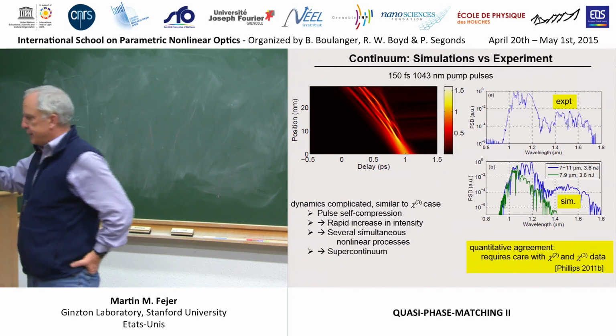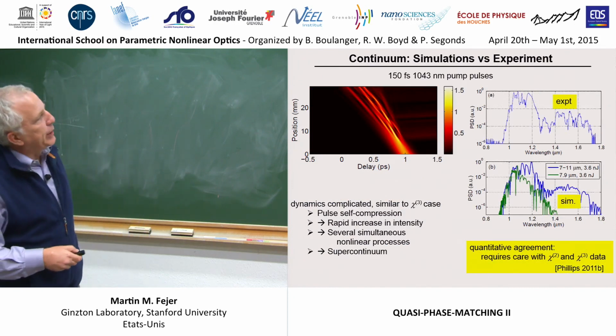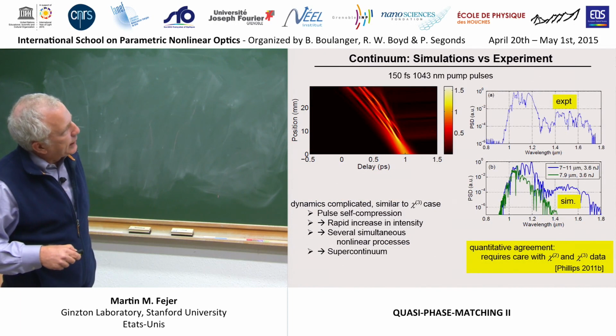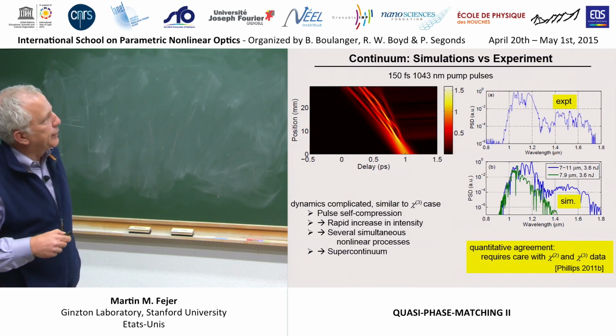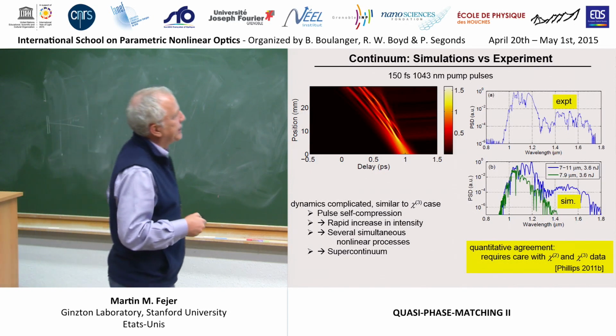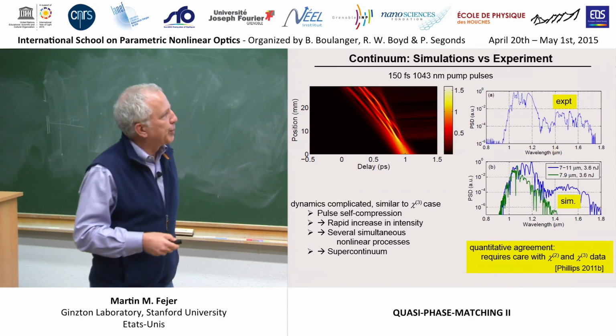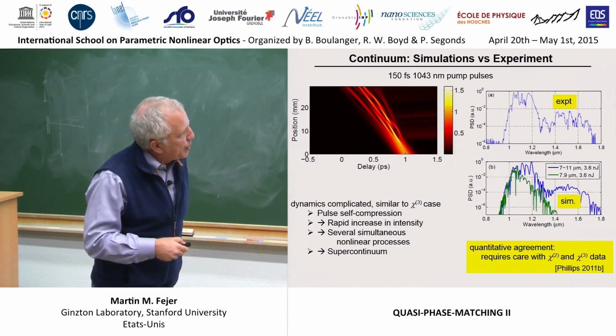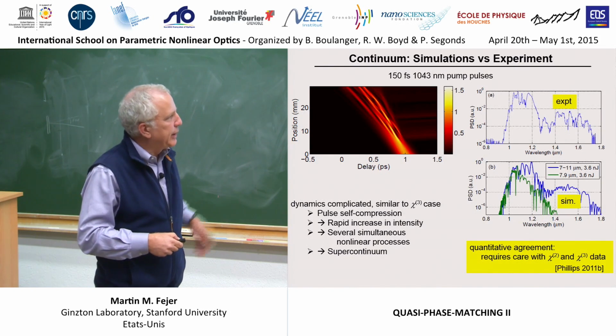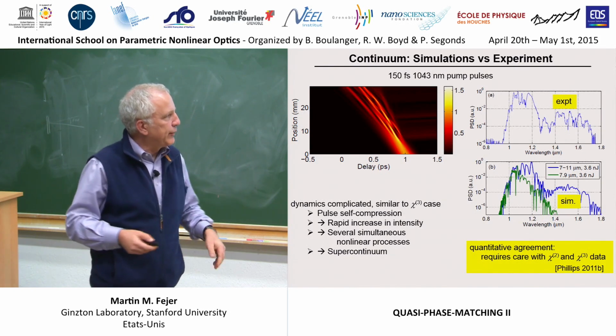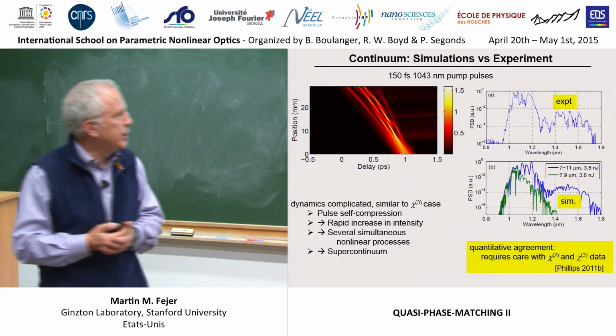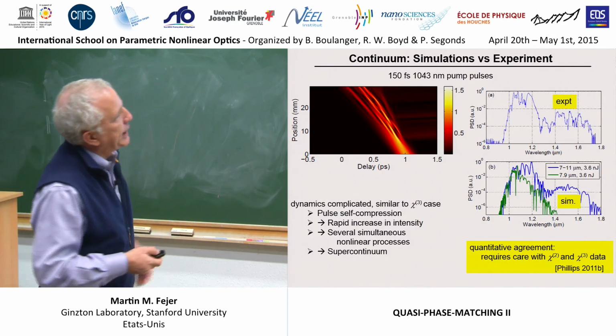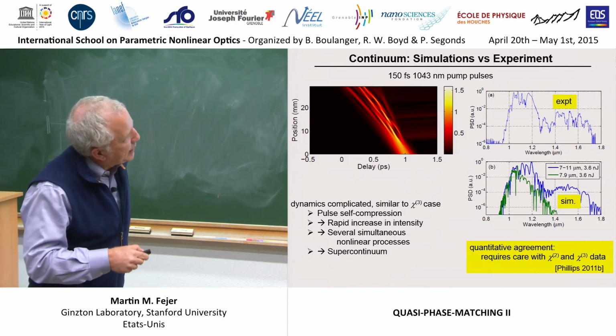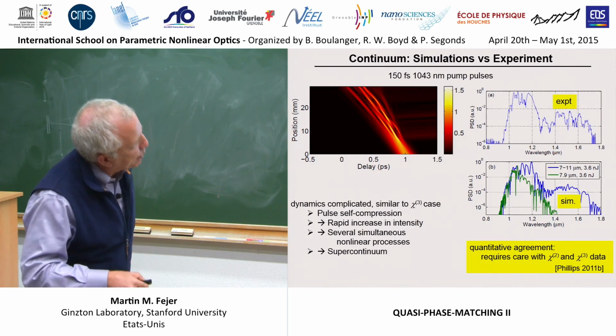Okay, but the upshot is not how cool the paper is, but how well does it work. Here's an experimental picture of a continuum generated with 150 femtosecond, 1043 nanometer pulses in QPM gratings that were chirped with two different rates, 7 to 11 microns or 7.9 microns - this one's unchirped. Comparing the chirp case here, the experiment and the theory look remarkably similar.